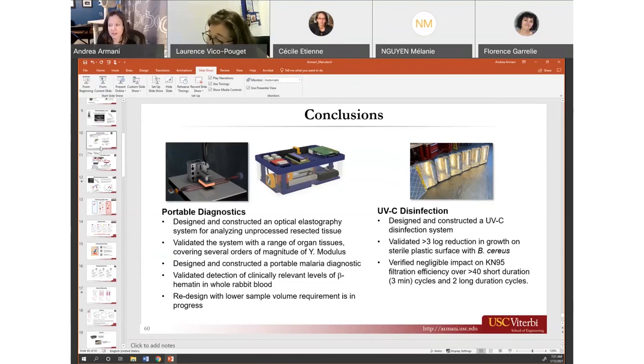Yeah, the sample stability is actually one reason why our human trials are going so slow. It's very hard. When we do the sample measurements, we have a really strict protocol. In some of the initial trials with the animal samples, we did a really systematic study looking at how the mechanical properties changed over time. So we did measurements every 30 minutes for 48 hours. And I have to give my PhD students credit for that, because it was every 30 minutes for 48 hours. So they took shifts on that.